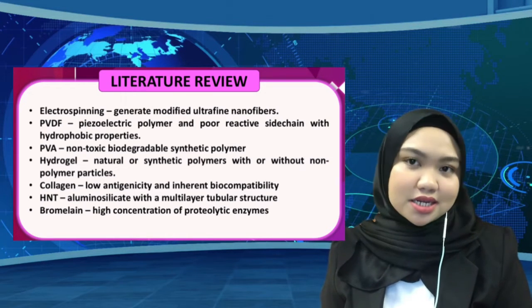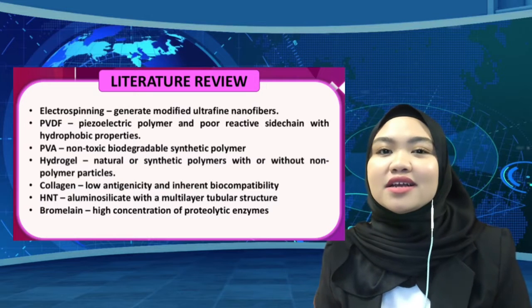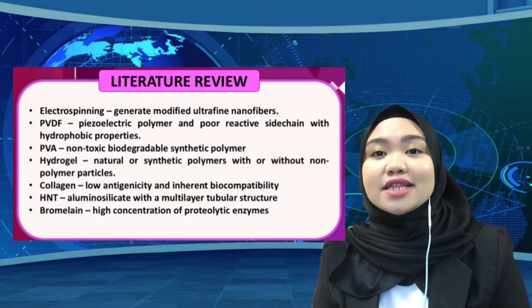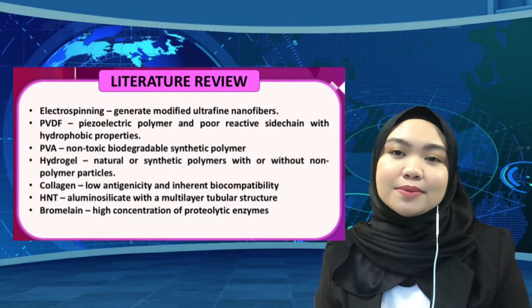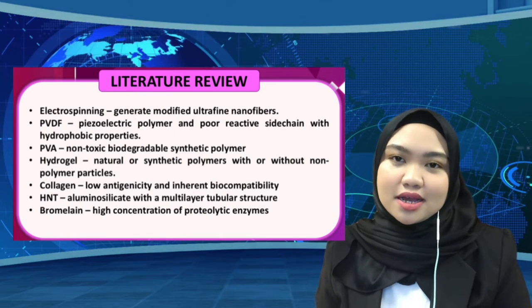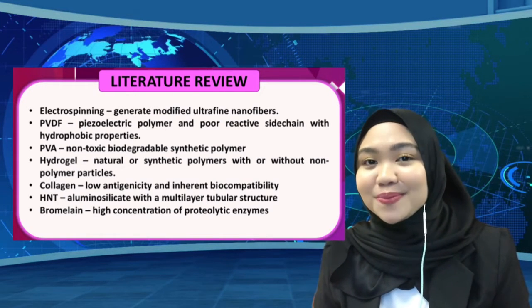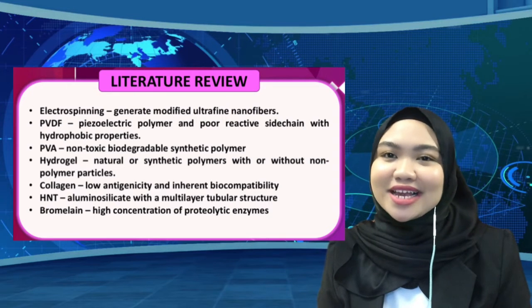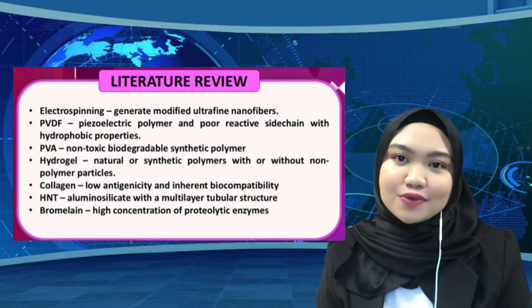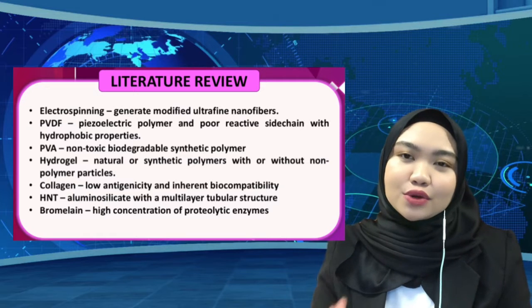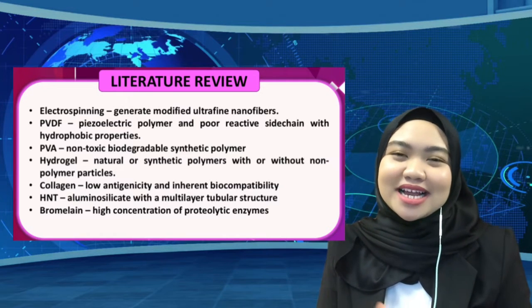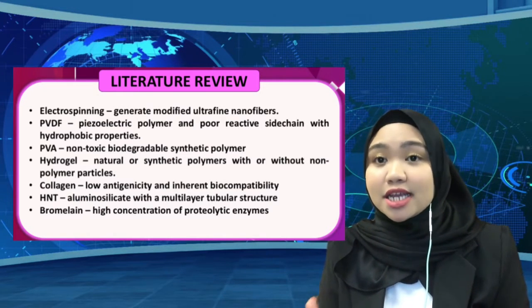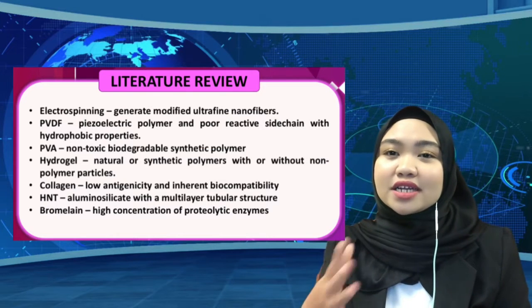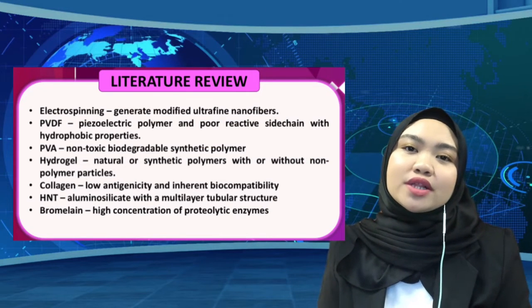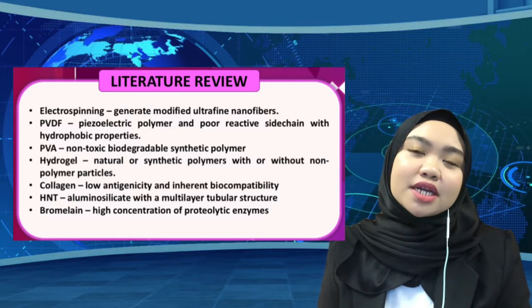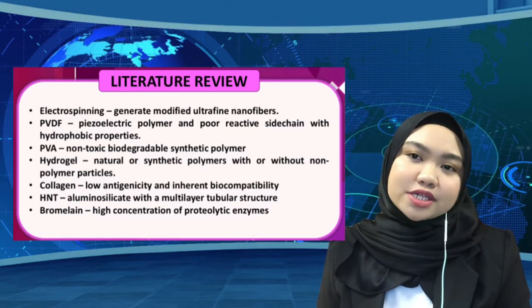This 3D cross-linked or interconnected polymeric network of fibers within a fluid system forms a sol-gel structure. For natural polymers, collagen is frequently used for surgical repair due to its low antigenicity and inherent biocompatibility with most endogenous tissues. HNT, or halloysite nanotube, is an aluminosilicate with a multi-layer tubular structure of a 1:1 layer. Multiple researchers reported that HNT can act as a reinforcement for the nanocomposite scaffold, which will directly result in the enhancement of the mechanical properties of the nanocomposite.